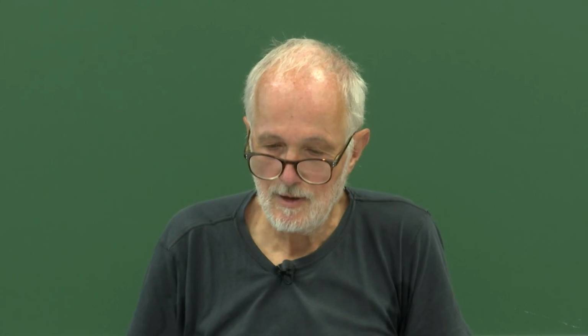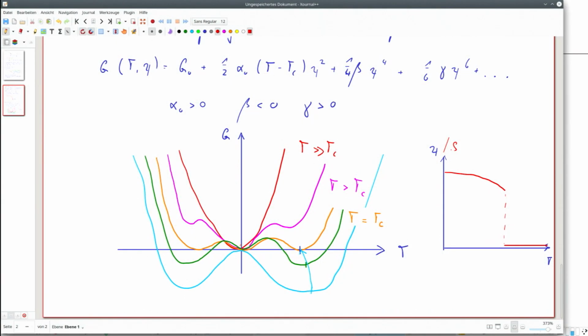That's the first point. But the second point, which is perhaps not that obvious from what I explained before, is, but it's known to everyone, I guess. So if you start in this low temperature phase, or we can also start in the high temperature phase, here at degree of order 0, now you develop this side minimum here. You have a minimum here, but still if you start in this disordered state, you would have to overcome this barrier here. This, I don't want to call it an activation energy, but there is a higher energy which has to be overcome to move from this degree of order to this degree of order.